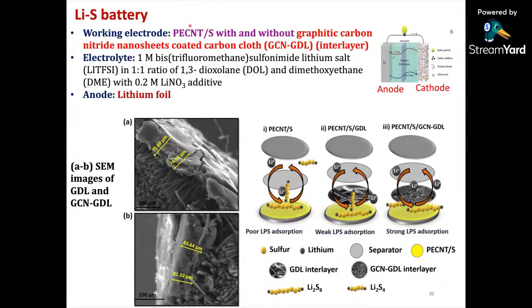Once we have done that, we come back to the lithium sulfur battery. So my cathode is now PECNT, which is a 2D carbon-based material with more or less 70 to 80% of the sulfur. So we fabricate the coin cell with PECNT-S with and without interlayer. You can see this is the PECNT-S without any interlayer. This is a separator, and we have added the interlayer. What is the interlayer?